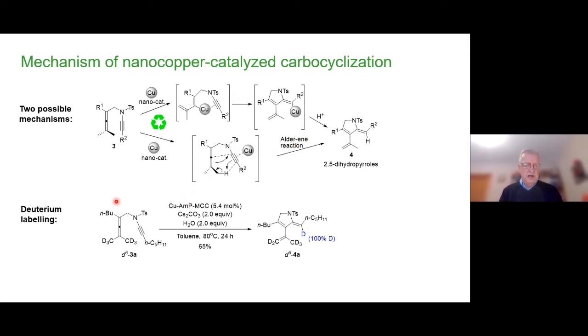So by deuterium labeling, where we put deuterium in these positions of the allene and run the reaction, we found that 100% of the deuterium actually came from the molecule, even though we have protons in the solution, so we can just rule out the above mechanism. So it's actually the lower mechanism here that operates.